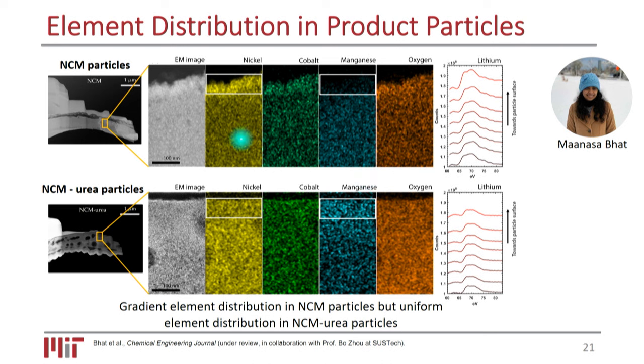And on this one, different color columns show you a simple component in element distribution along the radial direction. On the top, we see the NCM particles. And on the bottom, we see the NCM with the urea additives. The summary of the result would be, for the pure NCM particles, we do see some enrichment of the nickel component on the surface. So we do see a gradient structure from the surface to the center.